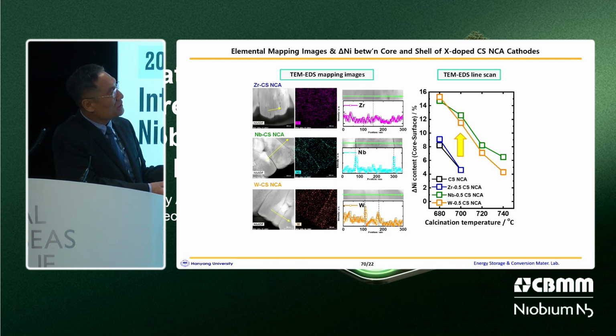Also, the nickel concentration difference between core and surface in the baseline and the zirconium-doped cathode rapidly decreased with increasing calcination temperature, whereas niobium doping considerably maintained the nickel concentration difference, even when calcined at 740 degrees Celsius, compared to others.